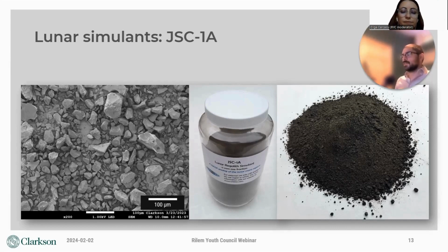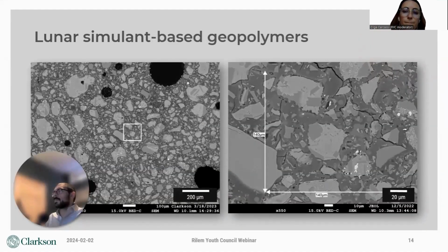We've used a variety of simulants, including the one I show here, which is JSC-1A, which stands for Johnson Space Center 1A. And even though this is made from terrestrial materials, the supplies are still quite limited. With JSC-1A, actually only 40 tons of the material were ever produced, and it's currently out of production. So these samples are still quite precious. Our colleagues at Penn State used JSC-1A and a variety of other simulants and a series of alkali activators to produce lunar simulant-based geopolymers. And again, they graciously shared some of the samples with us at Clarkson.